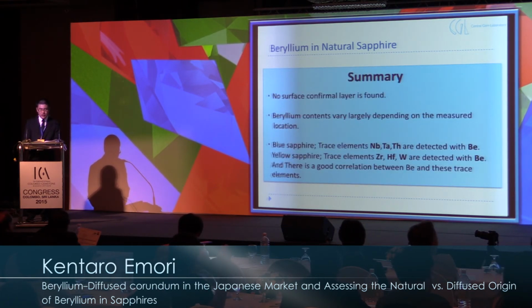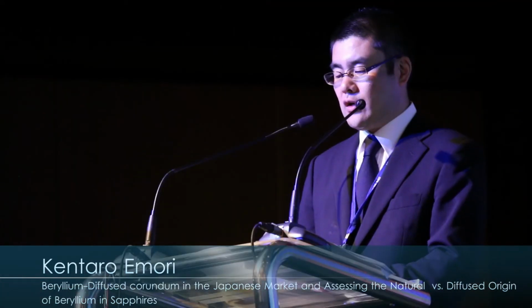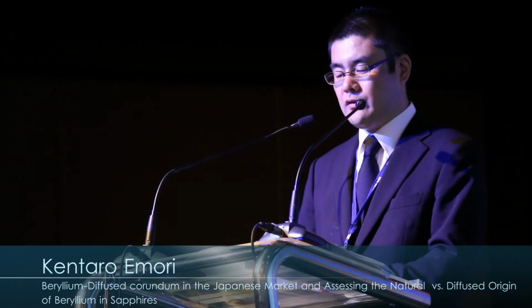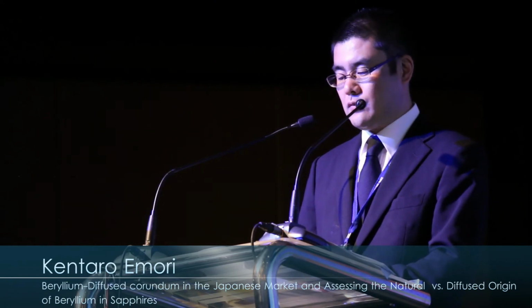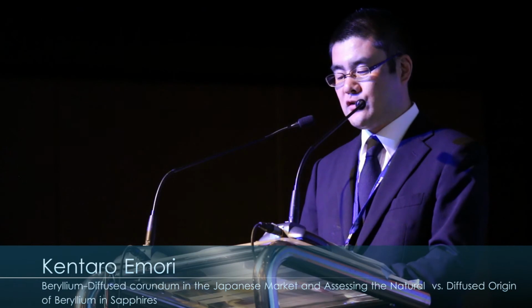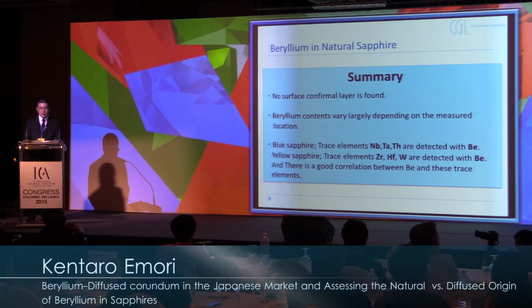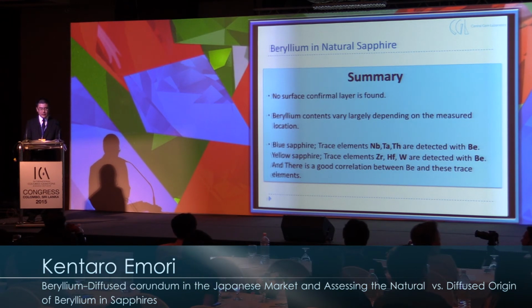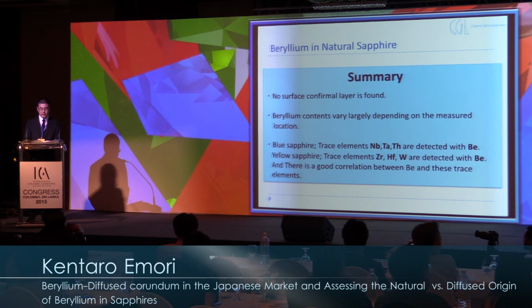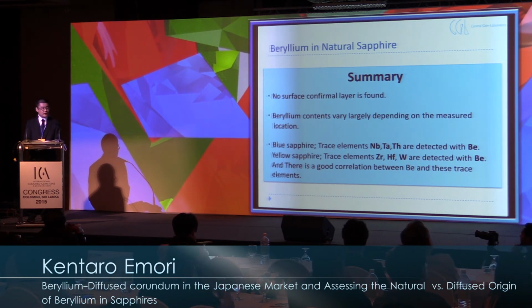Here is a summary of the identification of corundum with natural origin beryllium. No surface conformal layer is found. Beryllium contents vary largely depending on the measured location. Trace levels of niobium, tantalum, and thorium are detected with beryllium in blue sapphires. Trace levels of zirconium, hafnium, and tungsten are detected with beryllium in yellow sapphire. And there is a good correlation between beryllium and these trace elements.